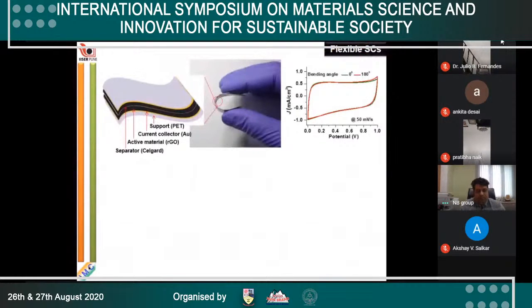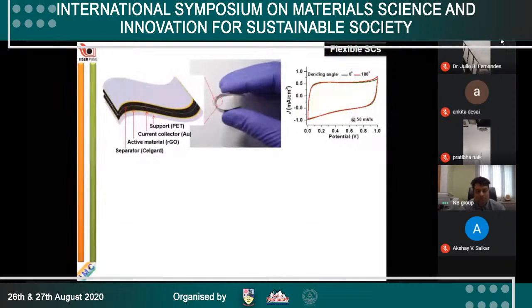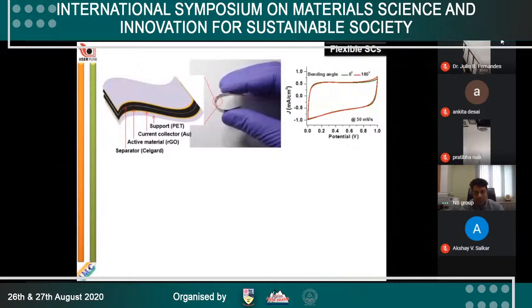We have fabricated flexible RGO supercapacitors by using current collector coated on plastic. Cyclic voltammograms are almost identical in stretching and bending modes. And in such stretching and bending modes, one can even go beyond 500 cycles. And the capacitance retention was found to be 100%.